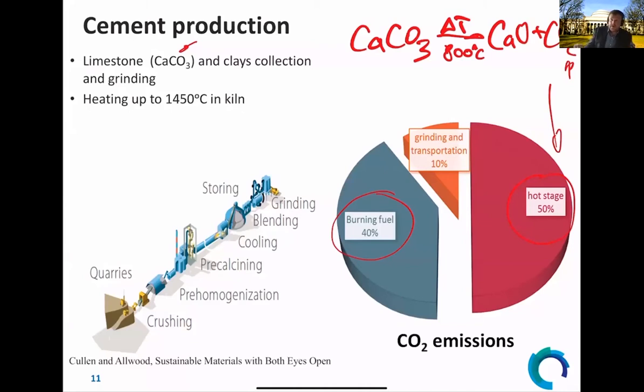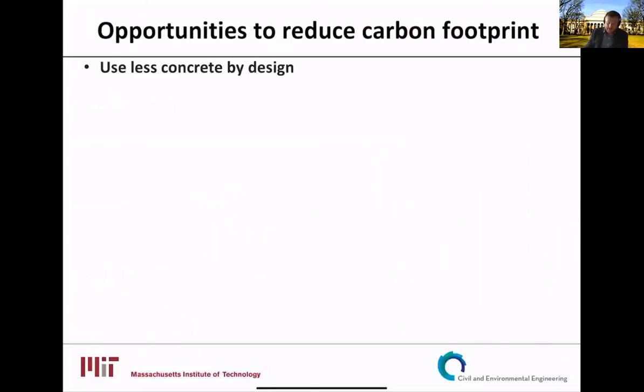The important issue with cement and clinker production is the temperature. It is the temperature we need to reach to make these reactions that produce clinker, and they arrive at 1450 degrees C. So this temperature is incredibly high and requires a lot of fuel. So our aim indeed is to work on those temperatures and reduce them, while making the same materials for the concrete. Good. So let me tell you a little bit about my opinions on how we can work on reducing the carbon footprint of cement.